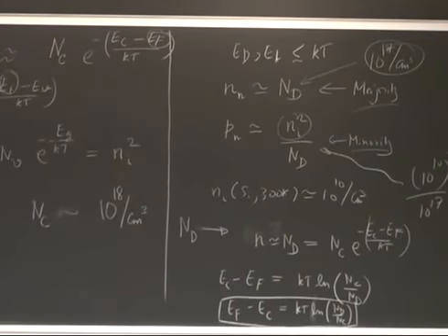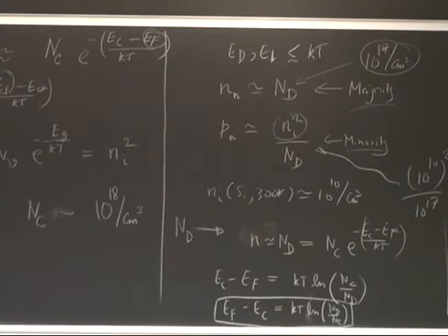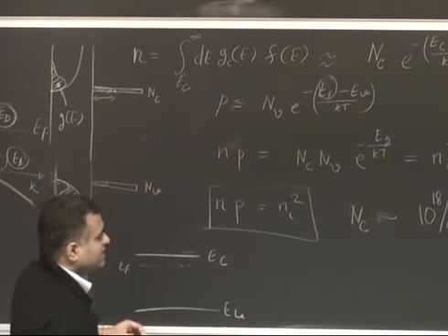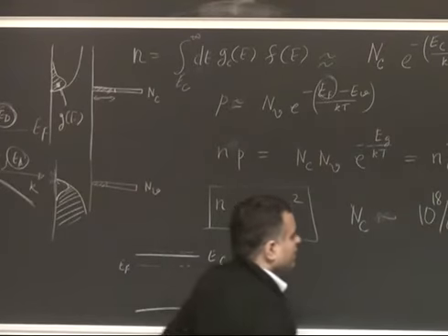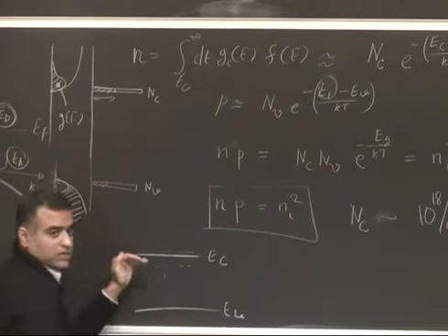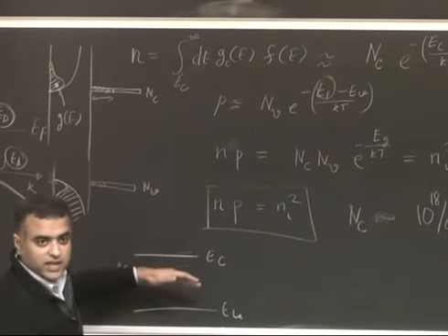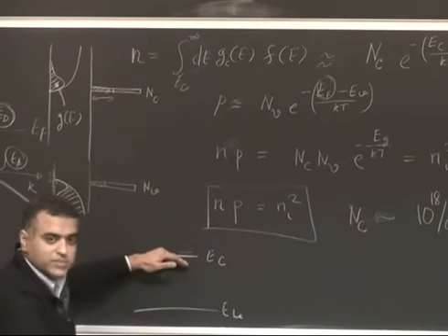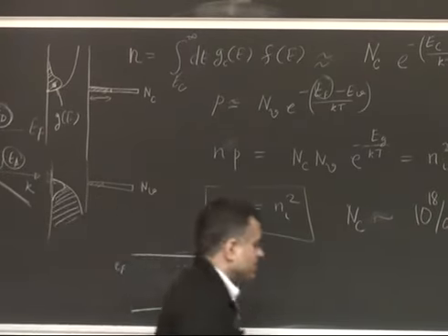When the doping density is lower than NC, the Fermi level sits below the band edge, and when it exceeds 10 to the power 18, the ratio becomes larger than 1 and the Fermi level enters the conduction band, or just about merges, and then goes further in at very high doping. The natural log function changes very fast at first, but once you hit the band edge it slows down quite a bit because the density of states is very high, and the carrier density is increasing linearly with doping, but the Fermi energy increases logarithmically with doping.